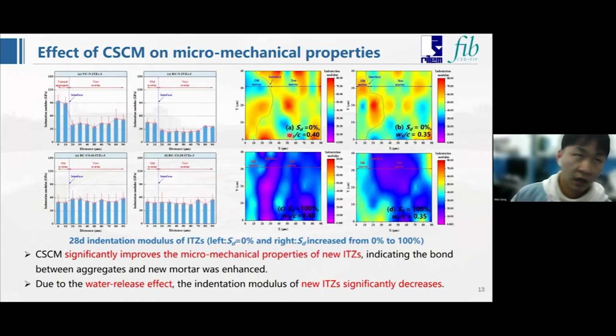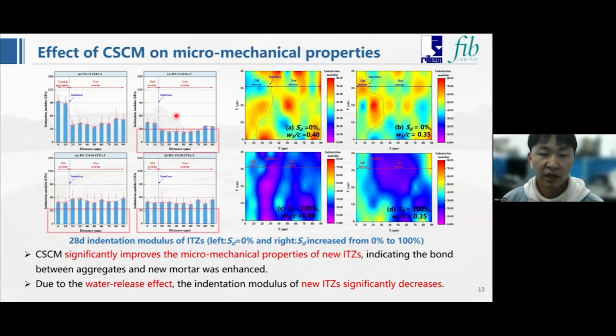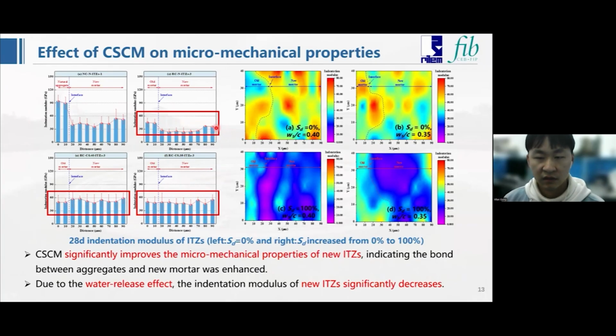And we conducted analysis from a micro perspective, and the result shows the CSCM significantly improves the micromechanical properties of the new ITZs, indicating the bond between aggregates and new mortar was enhanced. Besides, due to the water release effect, the indentation modulus of the new ITZs significantly decreased.